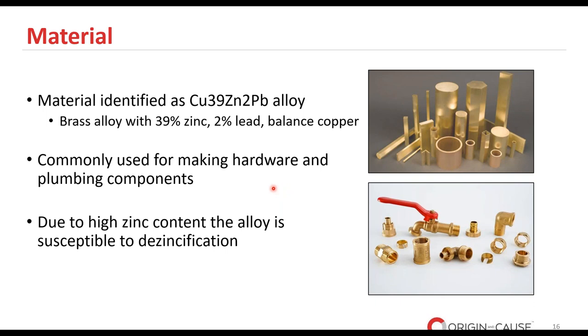One notable characteristic of this alloy is the high zinc content. While zinc gives our alloy certain strengths and benefits, it also makes the material more susceptible to de-zincification, or the removal of zinc for certain reasons. This process can weaken the alloy over time, and in certain environments lead to premature failure. So understanding this material's properties not only sheds light on its strengths, but also on potential areas of concern, guiding our ongoing investigation.